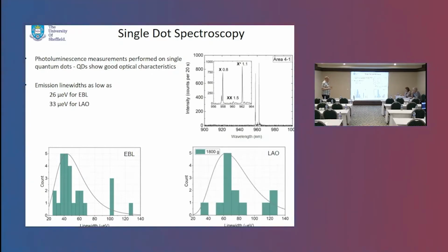If we look at the LAO, LAO doesn't let you grow as many dots. The statistics are clearly worse. The best line width is not that far away, which is substantially better than most other reports of LAO in the literature, where they've had to use 2 layers of dots. But the mode is sort of at 60.